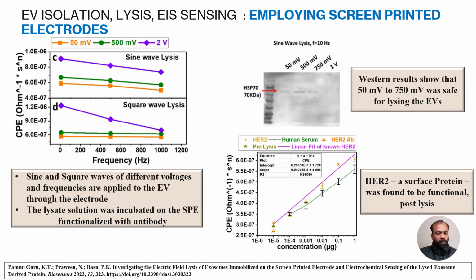We optimized the electrical lysing technique by using sinusoidal and square wave signals with different amplitude and frequencies, and we found that approximately 50 to 750 millivolts will be suitable for lysing the EVs. After lysing, the extracted HER2 protein was quantified by using electrochemical impedance sensing.